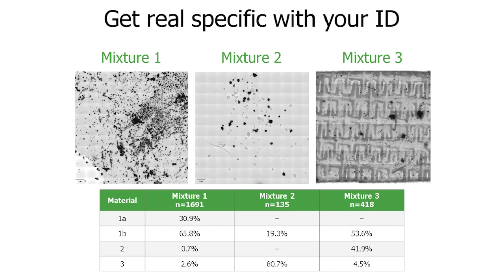All of these mixtures were analyzed automatically by Hound, and this was all actually quite fast. Mixture 1 had the most particles at about 1,700, and between imaging the sample, counting the particles, and identifying those 1,700 particles, Hound completed this in just about 90 minutes.